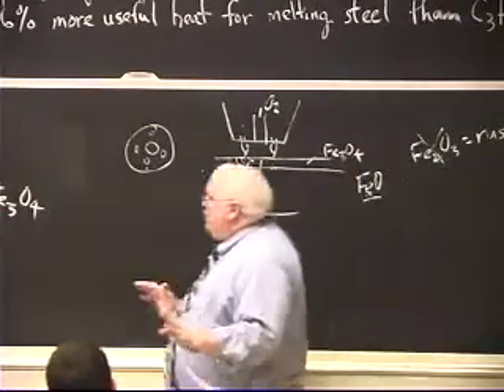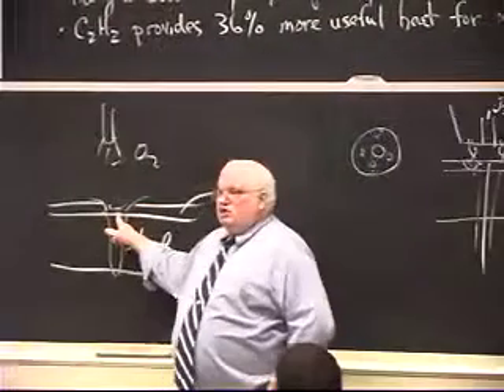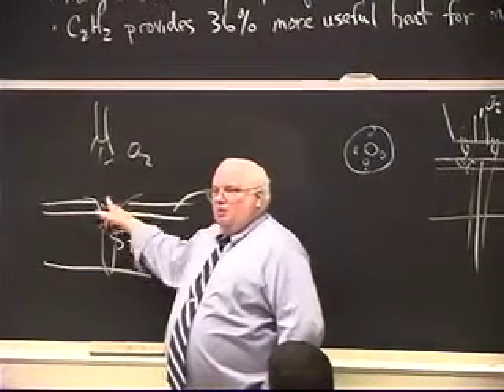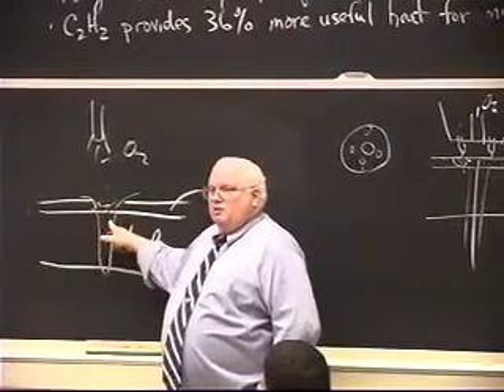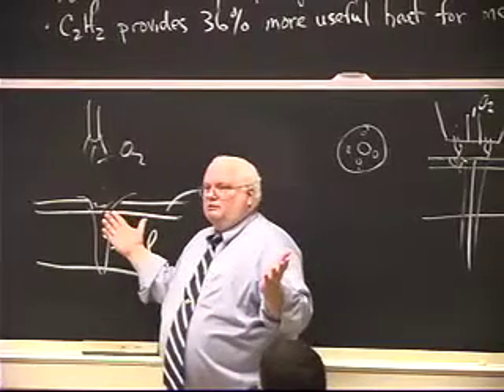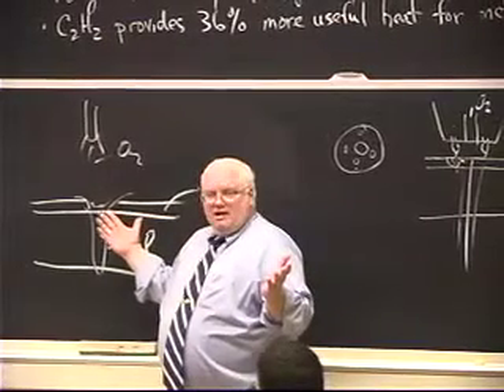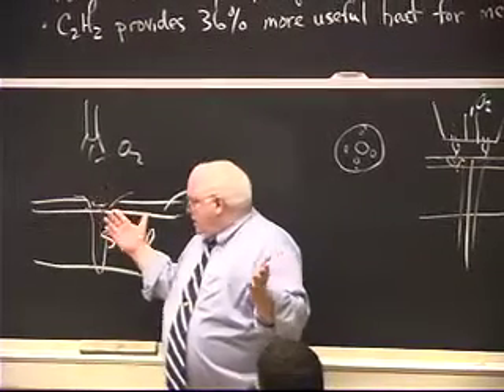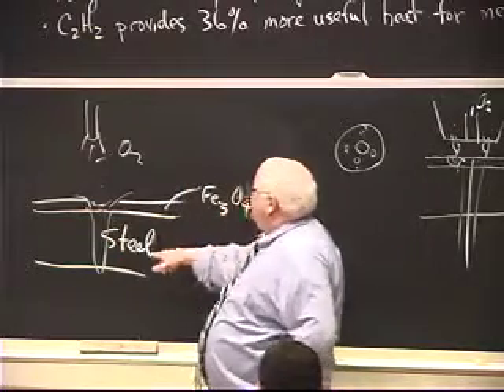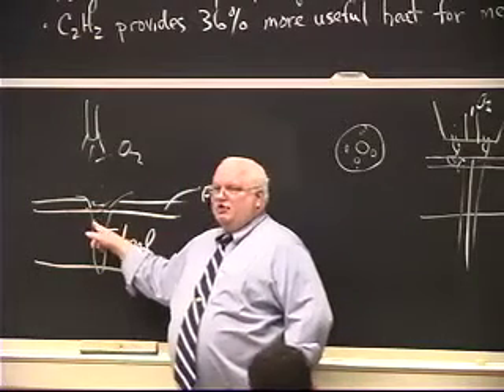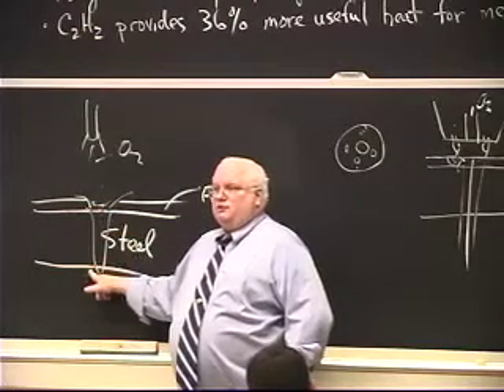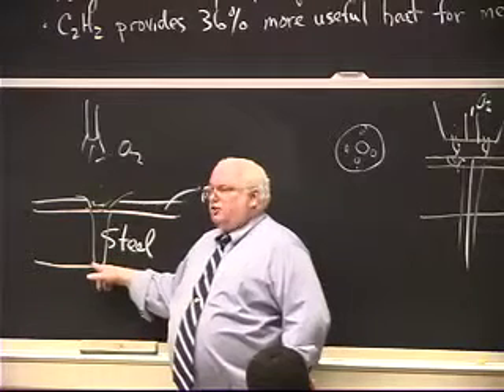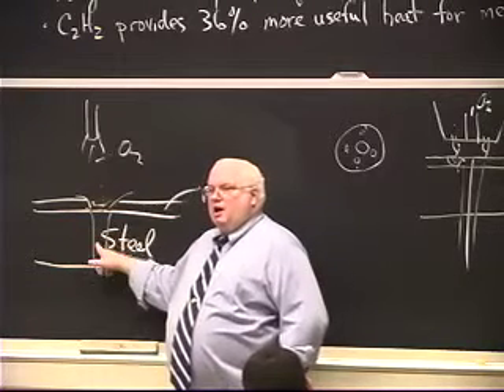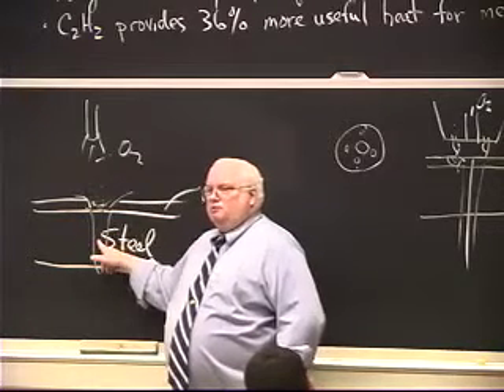What happens to the boundary layer here? It's pure oxygen in contact with steel, but the oxygen reacts to form a liquid. There's no gas boundary layer. I got rid of the boundary layer, and now this thing is no longer 2 to 10% efficient in heat transfer to the surface. It's near 100% efficient. I'm burning the iron to iron oxide. It literally is burning of steel.